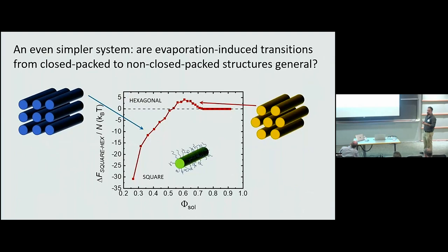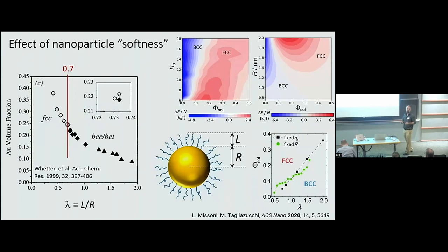And something that is also interesting is that we looked at an even simpler system, formed by very long, infinitely long rods. It's actually a two-dimensional system because, as I said, these are very long rods. And in this particular case, we also see a transition between this hexagonal structure, which would be close-packed if these were hard bodies, and this square one. So I do believe there is some generality here in terms of this transition between something that would be close-packed when you have solvent to something that is not when you don't. This is something we are working on, but maybe it may be interesting to look at that problem in binary superlattices, for example, and see if you get the same.